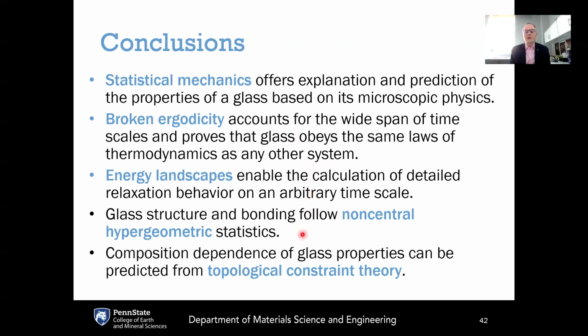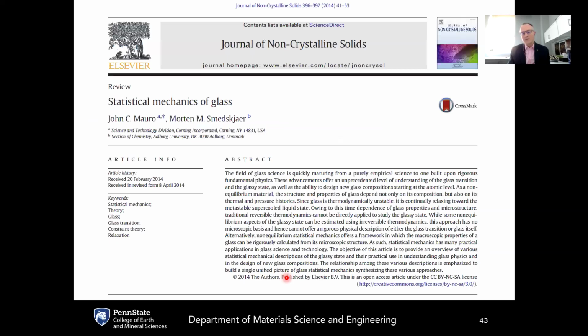And then if we look at the structure of glass, the non-crystalline structure of glass can be described in terms of probability distributions that follow non-central hypergeometric statistics. And if we calculate that, we can plug it into topological constraint theory, and specifically temperature-dependent constraint theory, to calculate properties. So this gives us the framework to go from the really basic underlying physics of the non-ergodicity of glass up through understanding the distribution of glass structure and bonding, connecting that then to the connectivity of the glass network and the number of rigid constraints or degrees of freedom, and then the properties of glass. And this, we're just scratching the surface here.